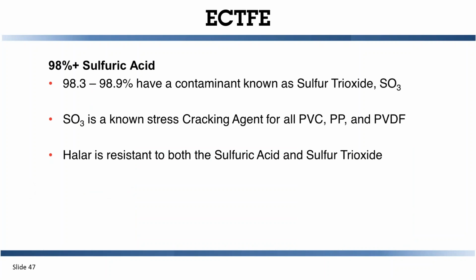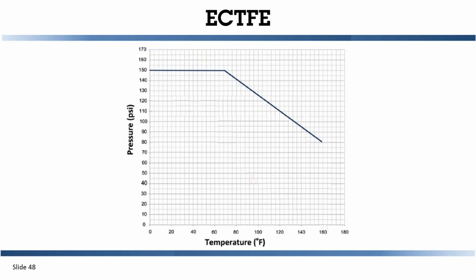+98% sulfuric acid has a contaminant known as sulfur trioxide. Sulfur trioxide is a known stress cracking agent for all PVC, PP, and PVDF. Halar is resistant to both sulfuric acid and the sulfur trioxide. That's what gives us the confidence to apply that for these applications. Pressure rating versus temperature, 150 psi at ambient temperature, and the known temperature range is above 150 and increasing as we get more information about ECTFE.